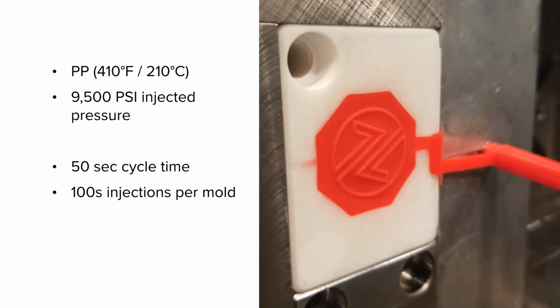So one of the questions in the Q&A was asking regarding why are your cycle times lower? Well, part of it is you can't get the heat out, but some of it is the nature of it's a very manual and labor intensive process to pull the stack, manually disassemble it and reassemble. So Jake was running in semi-automatic. We do molds like that, but when we're running something of this nature, we were manually taking that core out. So it's not a very fast cycle time. I think we could be molding, maybe 35 to 40 seconds if you were able to really speed that demolding process up. And then, as said before, we saw hundreds of shots. We were extremely pleased because a lot of our customers are just trying to get a product developed and get 40, 50 samples in hand so you can assemble, test with real molded parts.